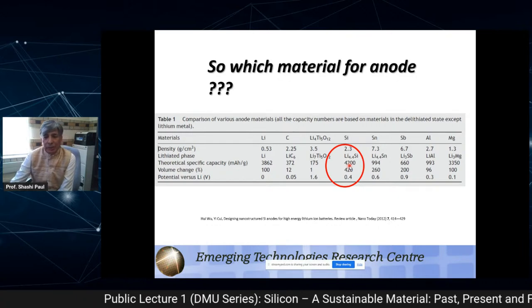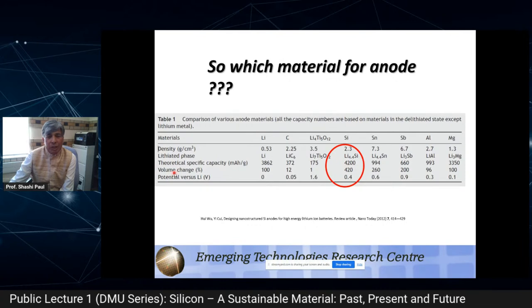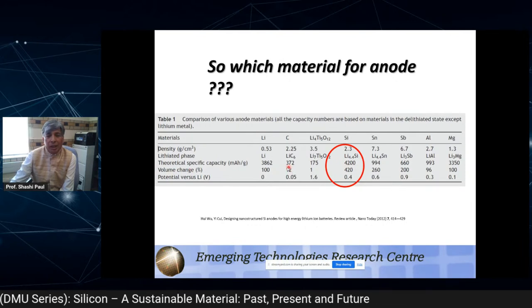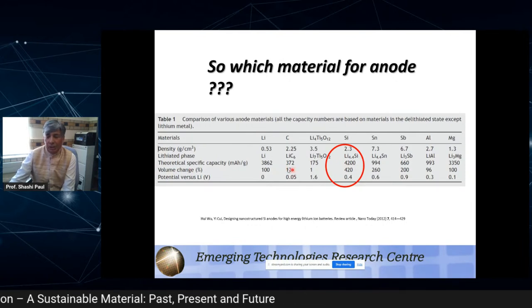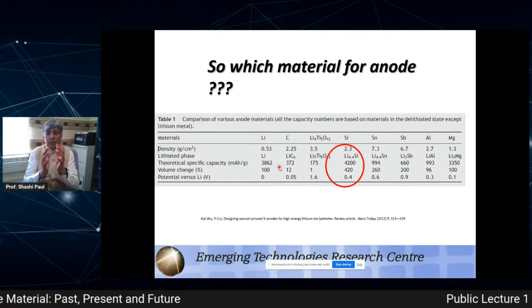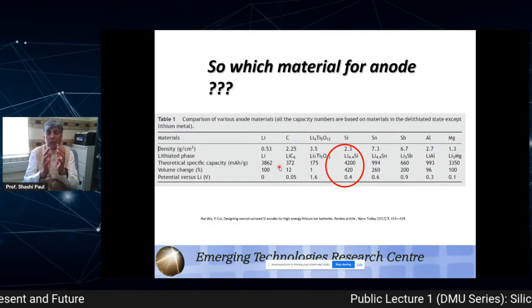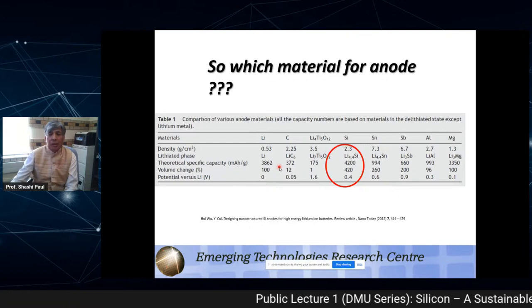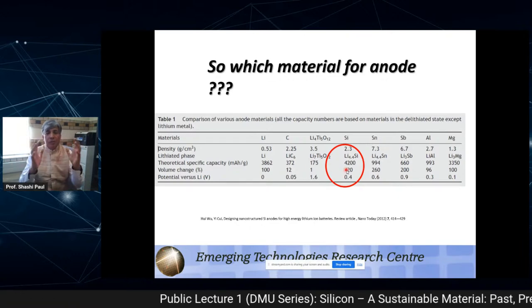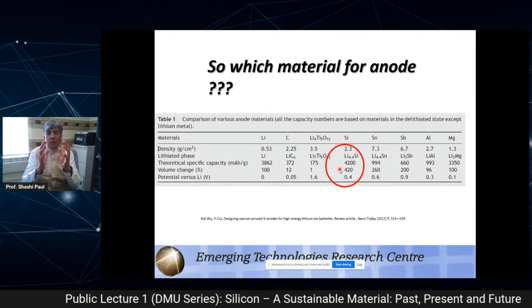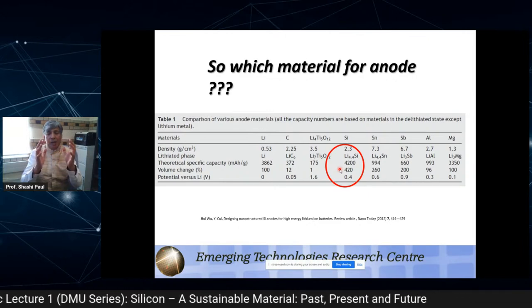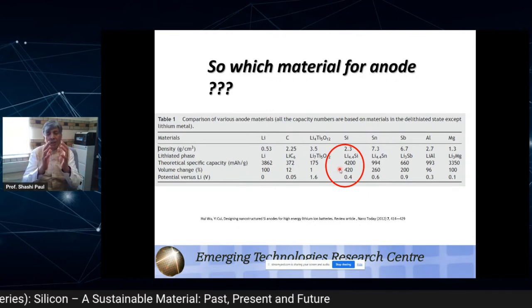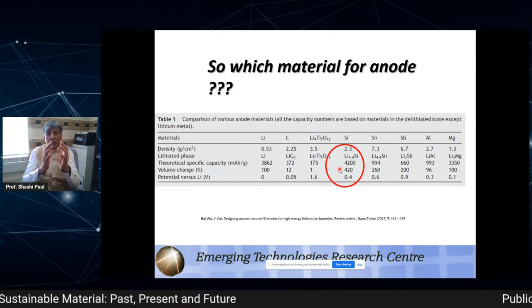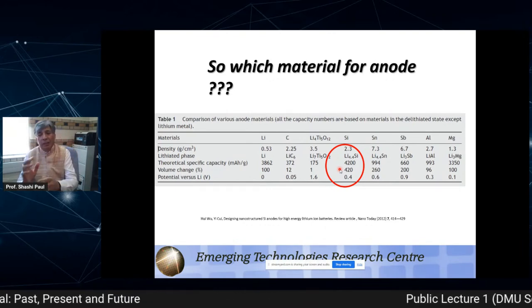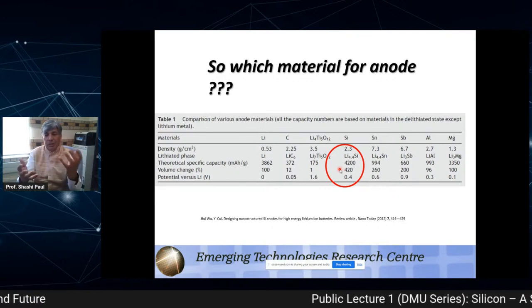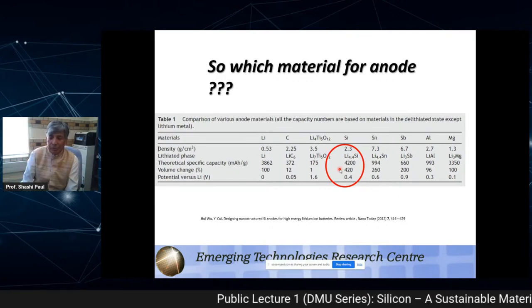But the problem with silicon is this one. If you focus on volume change, when these ions go into carbon, there is a volume expansion. So there is a little expansion. Its volume expands around 12%. But silicon, it is like a 400% expansion. So when you charge, it expands, when you discharge, it contracts. So this expansion and contraction lead to the crack formation in the silicon, and finally failure of this battery.